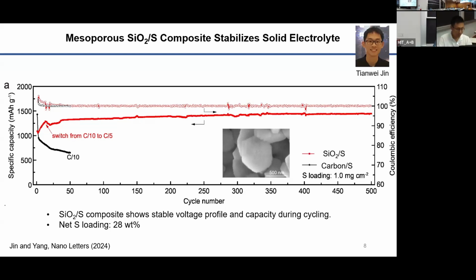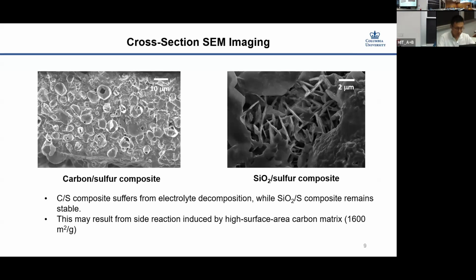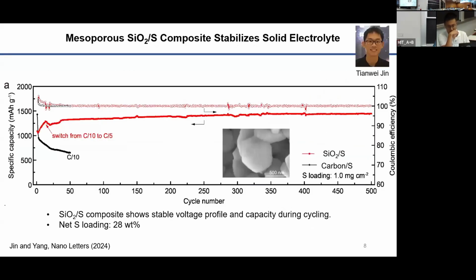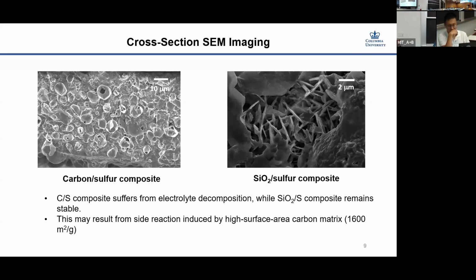And here is the carbon case. We get a better idea when we look at the cross section of the all-solid-state pellet. With the silicon dioxide matrix, you can still see these flakes, which have basically the same morphology as the electrolyte flakes. That means the electrolyte is intact, and the silicon dioxide matrix does not cause massive decomposition of the solid electrolyte. But on the other side, with the conventional carbon composite, you can no longer see the flake configuration. You just see lots of voids. This is due to the decomposition of the solid electrolyte, which forms new phases and thus causes the volume to change. So we can see here that the insulating nature of the silicon dioxide is really helpful.